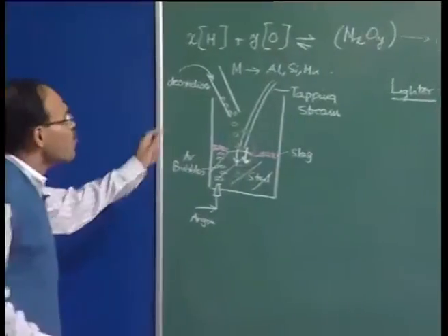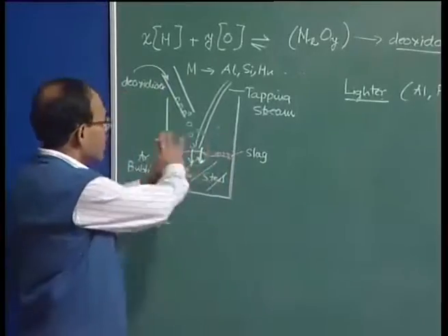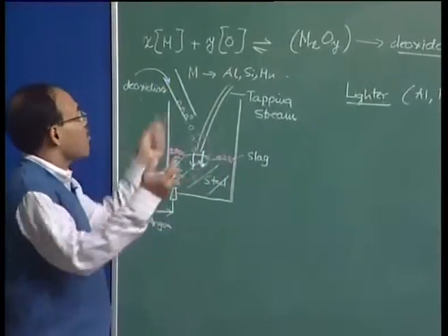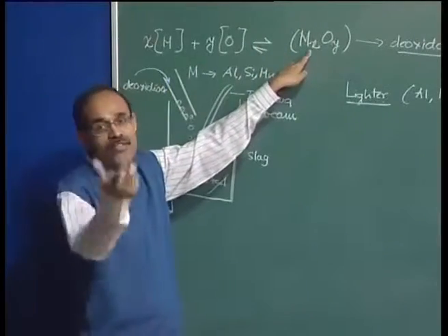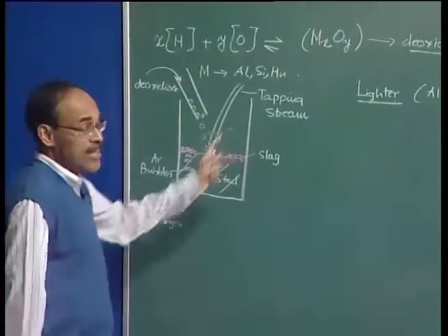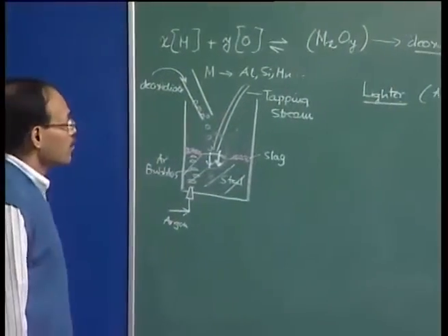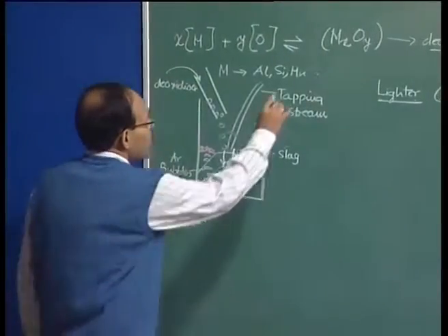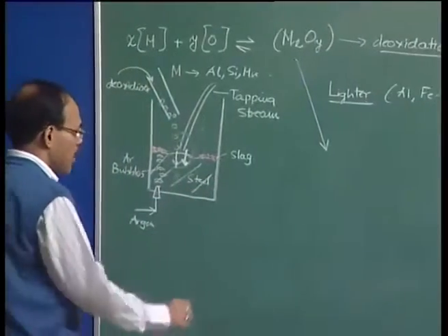And if we assume that the deoxidation product is in pure state, okay, so that means there is no compound formation here. If aluminum is added, aluminum reacts with oxygen and pure aluminum oxide forms. There is no calcium aluminate or aluminum silicate, etc. No other phases are present. In that case, we can consider that the activity of the deoxidation product is going to be 1. And if we write down under equilibrium, if we assume that the reaction is under equilibrium,